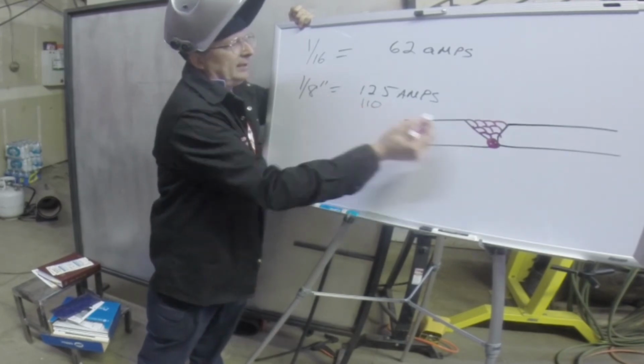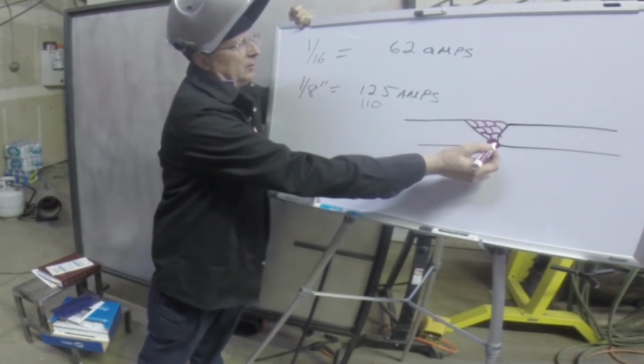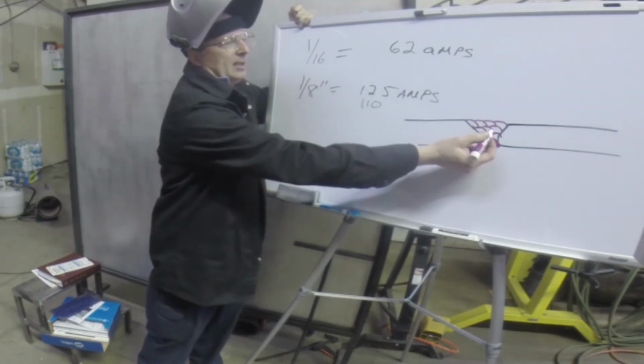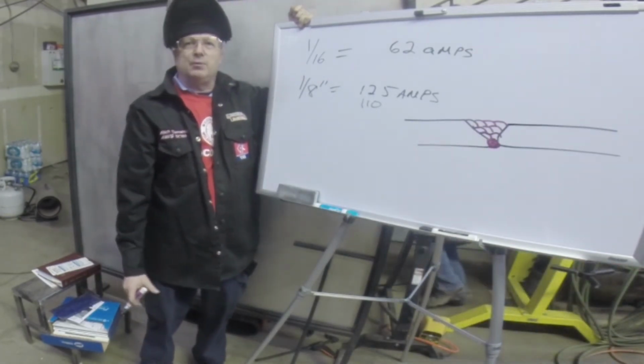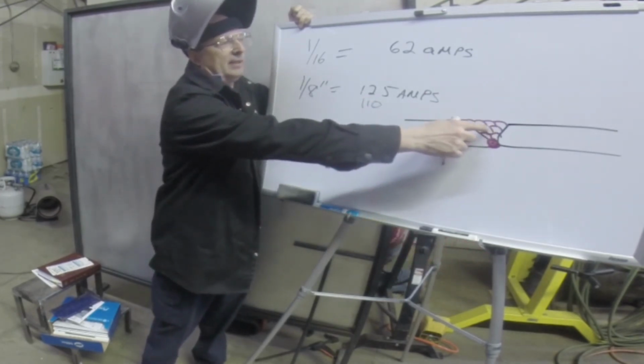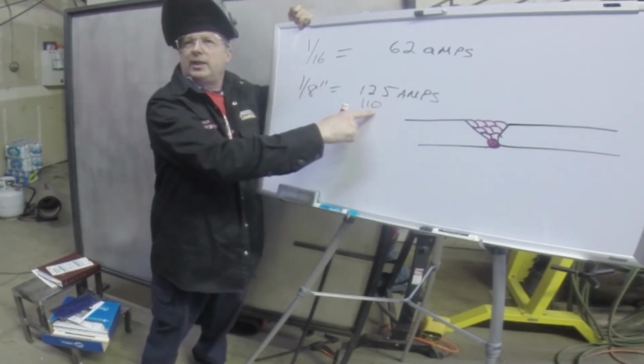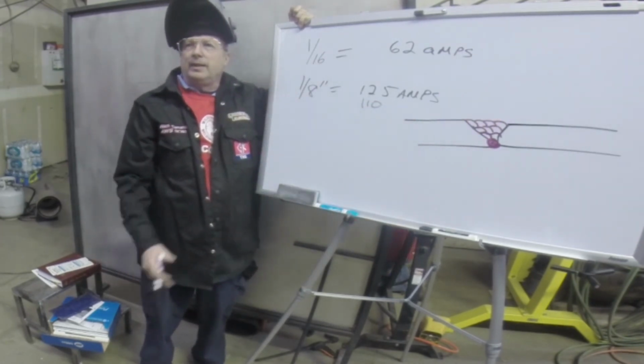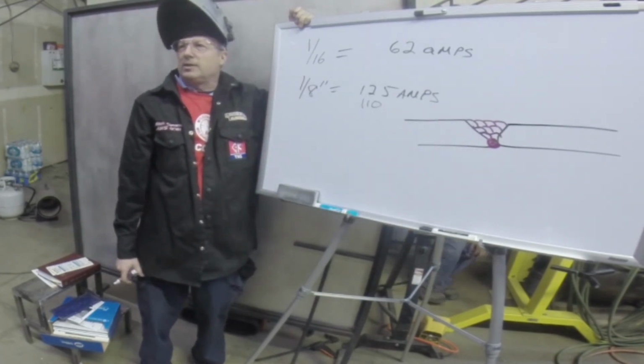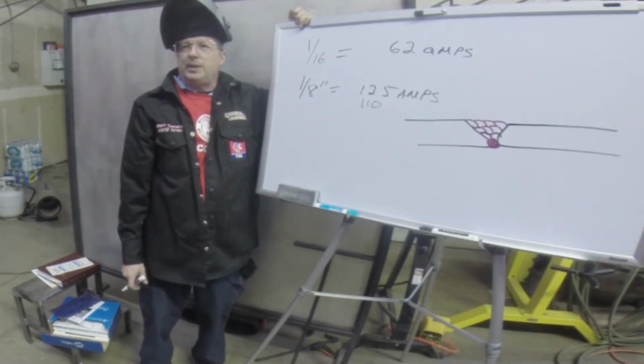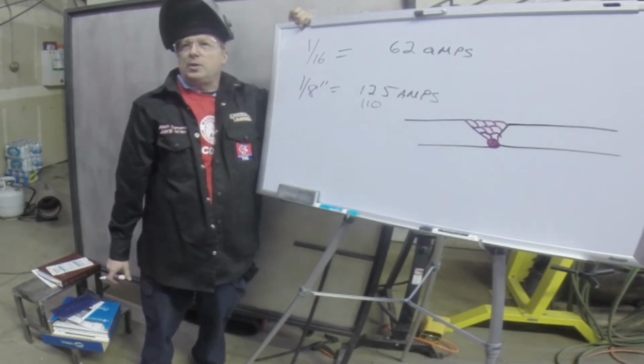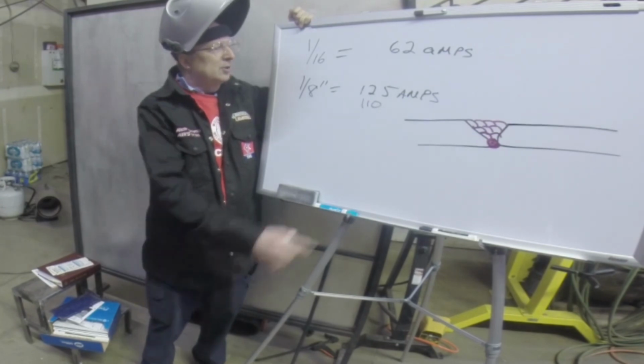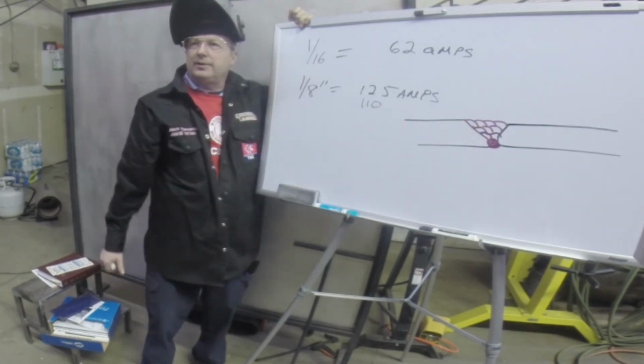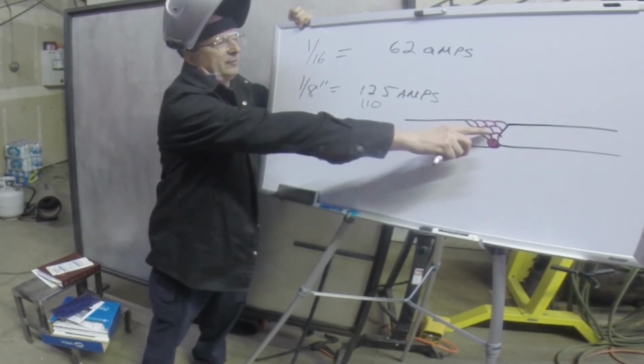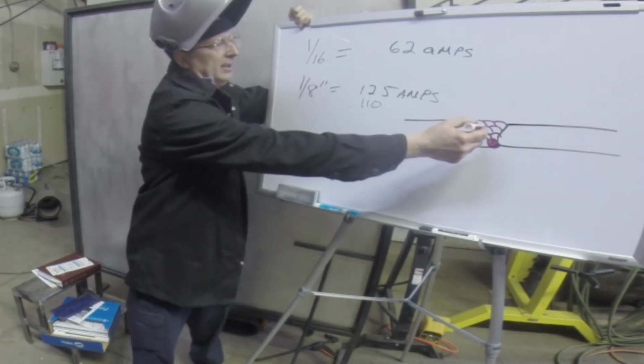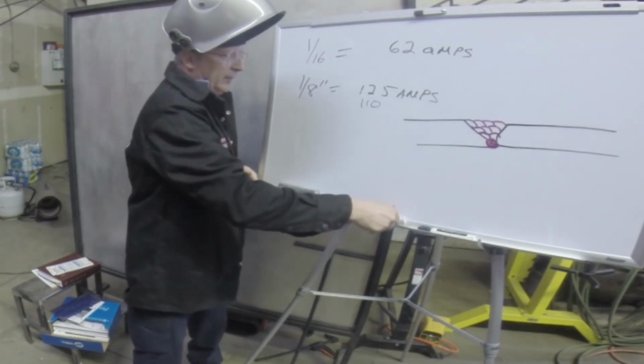If we're doing 1/8 inch stick rod in here, we do 110 amps there. We can crank this up on these filler passes, usually 5 to 10 more amps. We might even be able to get up to 125 to run these fill passes. Then we'll drop it back down to 110 amps on the cover passes, and that way you don't get a bunch of undercut. Nice idea, a little bit cooler. The welding inspector will disqualify your weld if you get a lot of undercut. So you can adjust these as you weld on thick plates. You can usually jump it up on your fill passes, but again, this is a bunch of stringers. Now, if you look at some old